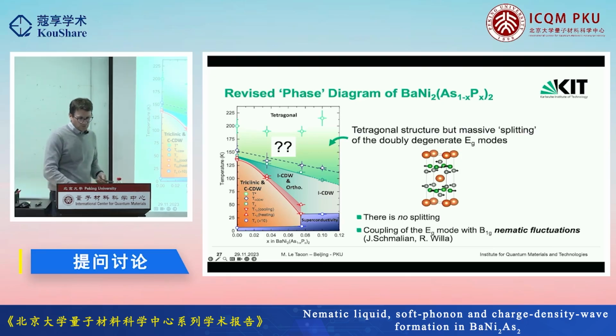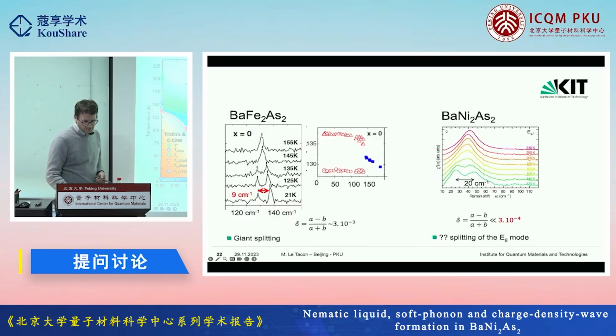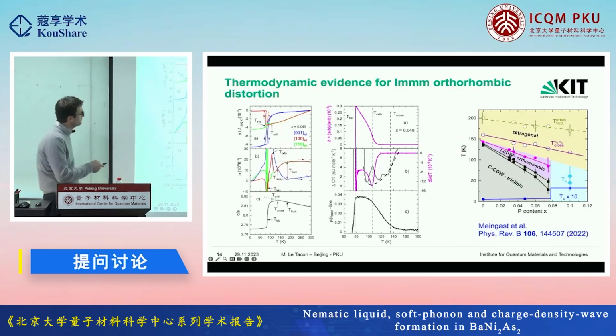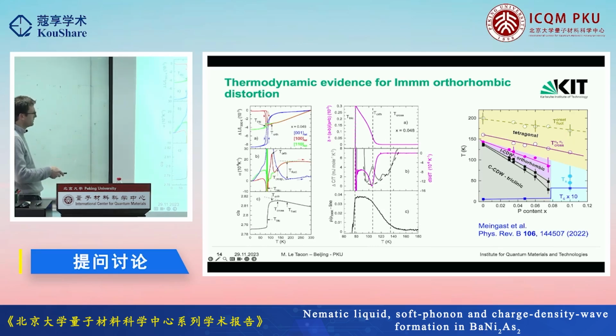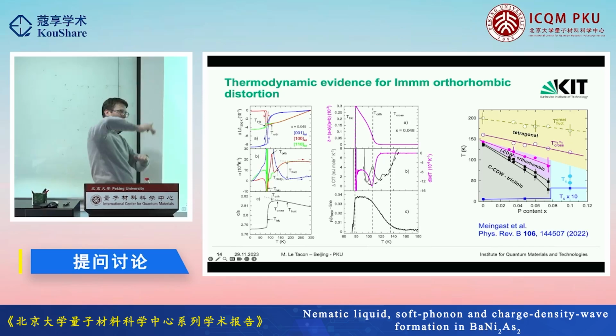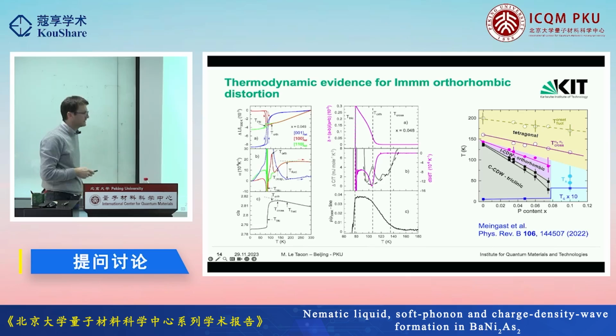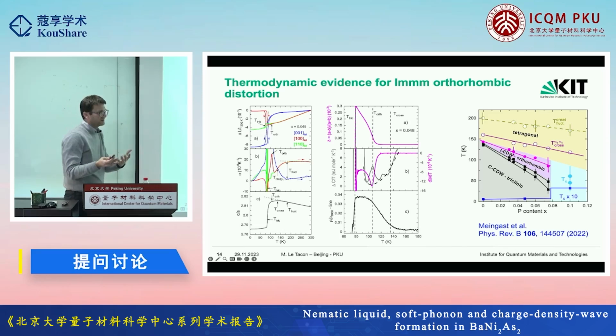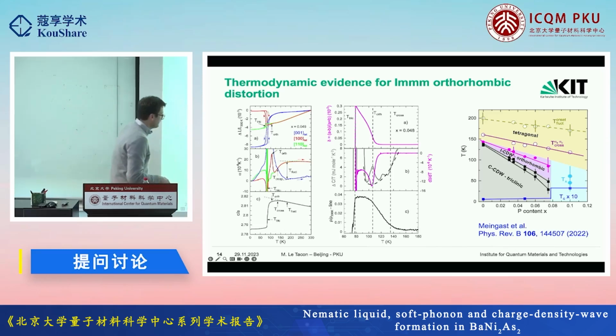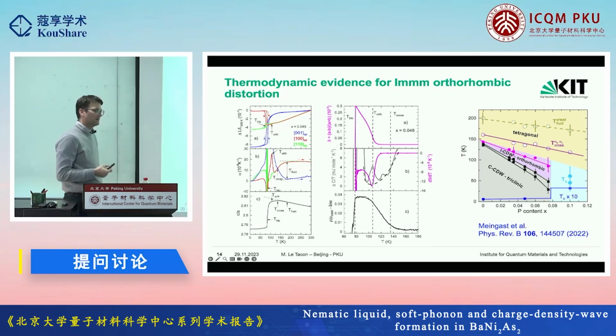From the thermodynamic point of view, we don't see a real signature of that, and the only thing we can really see, maybe I have it here in the paper of Christophe, is some kind of fluctuation in the C/A ratio. The take-home message here is that in all these kinds of systems, the C/A is very important in controlling the electronic phase of the material. And the only thing that we see at high temperature here is a deviation from an already anomalous behavior. The C/A ratio is increasing with cooling, but the rate at which it increases seems to step down here. It doesn't tell us anything about whether it's a nematic or something like that, but that's the only other evidence we have that something is happening above those transitions from the structure. But the structure remains really tetragonal.